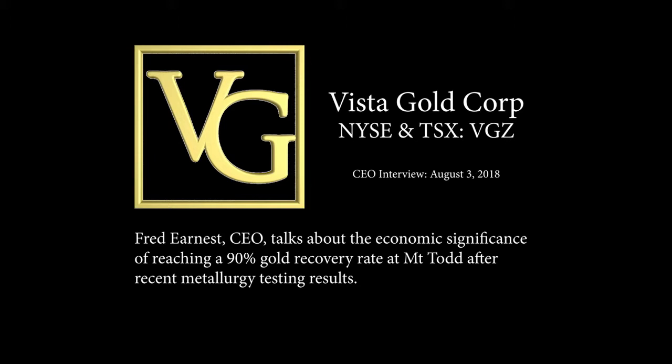Now, I think it's important for the listeners to understand that there's some exciting news that could follow this. The reason is that in achieving the 90% recovery at the grind sizes that we're talking about, and there's still more test work to be done to completely confirm and validate this, we did this on a low-grade sample, two different composites. Their average grade was 0.65 and 0.66 grams per ton. That's below our average grade. It's about halfway between the cutoff grade and the average grade.